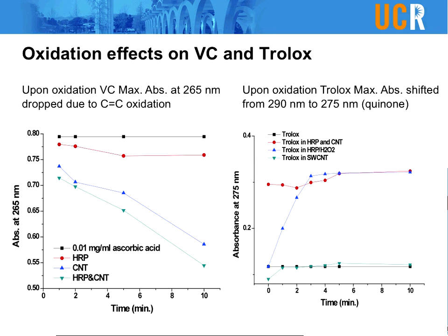It could only be oxidized when HRP is added to the solution, which means it's what we later found out is the hydrogen peroxide. So with the CNT itself, it was not oxidized, but it suppressed the oxidation of DCFH right away. And with the addition of the HRP, the Trolox will be oxidized by HRP and the hydrogen peroxide generated by the CNT solution.